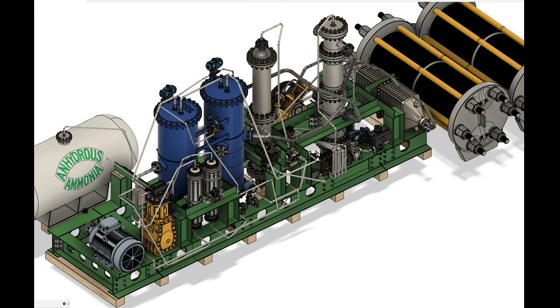Diaphragm compressors suffer from premature diaphragm failure, attributable to sharp thermal gradients experienced when reaching operating temperature from static temperature. As mentioned earlier, the diaphragms are constructed from very thin, smooth stainless steel discs, which flex only a small amount up and down, driven by hydraulic oil. To minimize the risk of gas-oil cross-contamination, 3 discs are usually used simultaneously. While the disc is quite reliable during steady-state operation, it suffers from premature thermal-induced fatigue failures if cycled excessively.